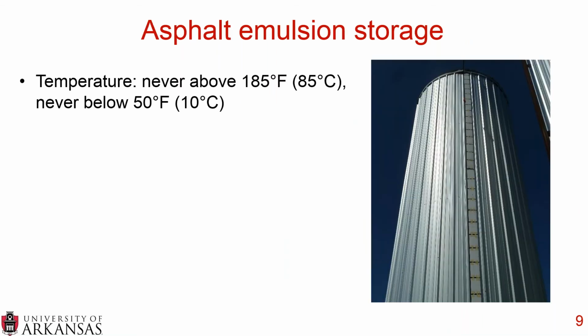Now for the asphalt emulsion storage, this varies greatly. The temperature varies greatly on the grade of asphalt emulsion, and I'm not going to get into those details, but a couple rules of thumb. You never want the temperature to go above 185 degrees Fahrenheit. That's because you're starting to get close to the boiling temperature of water. And asphalt emulsion is 33% water. So if you boil asphalt emulsion, you'll boil the water and you'll just have the asphalt binder left and you'll lose your asphalt emulsion and you can't just put the water back.